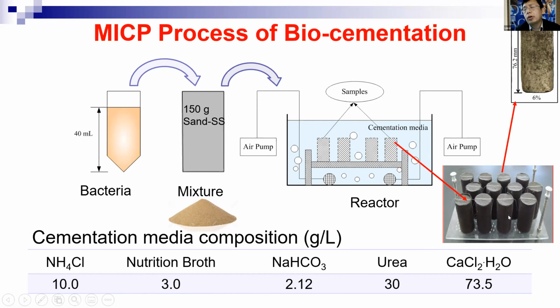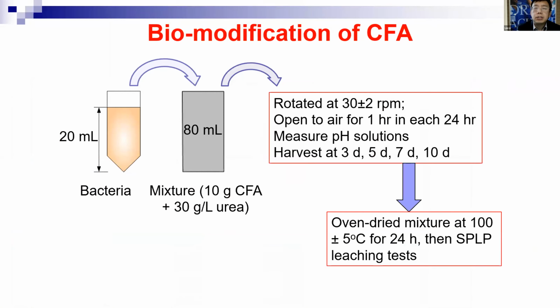For this immersive method, the biggest sample size we can run depends on the solution you have. So we keep this to less than 4-inch diameters. If you say I want to make a big sample, then you probably have to use the injection method.